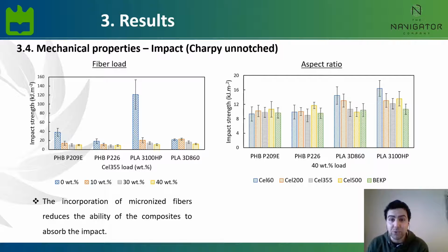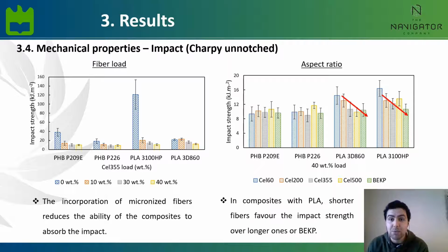On the effect of the aspect ratio, smaller fibers seem to favor the impact strength in composites with PLA. On the opposite, in composites with PHB, the aspect ratio of the fibers had little effect.